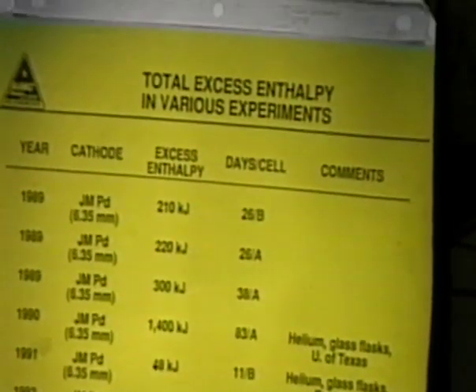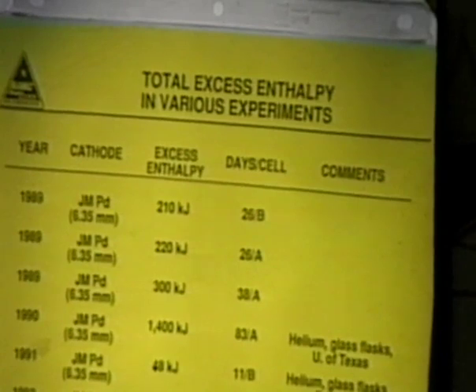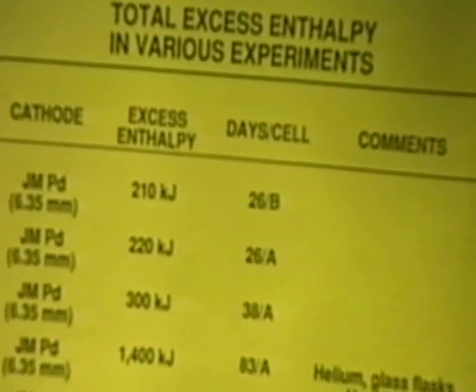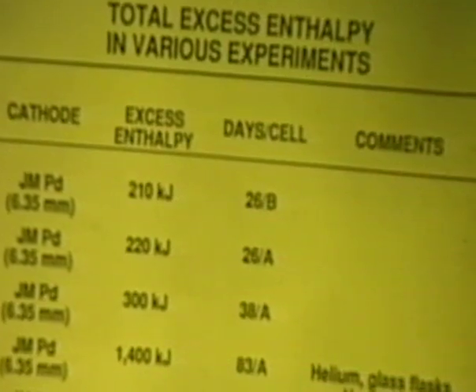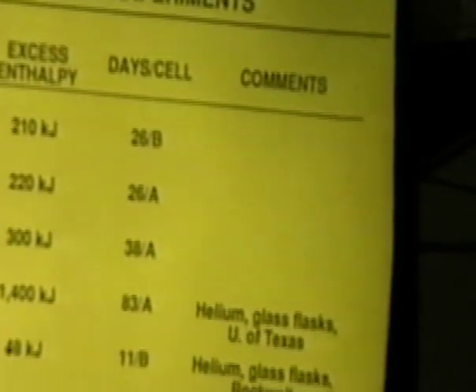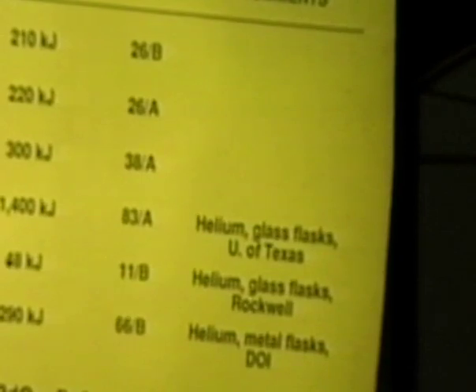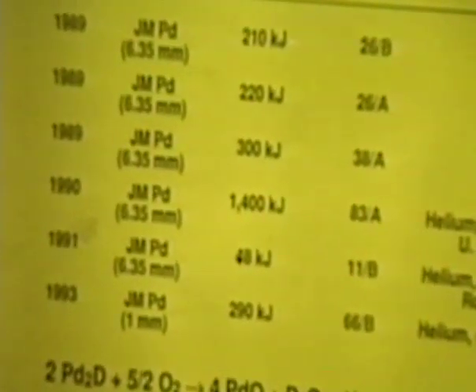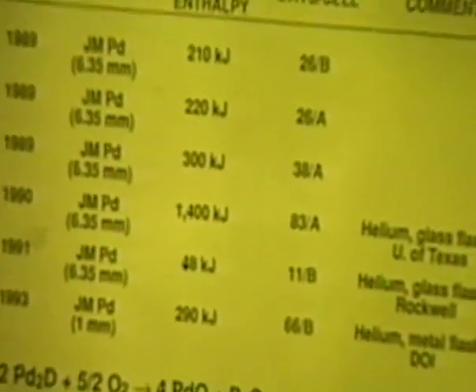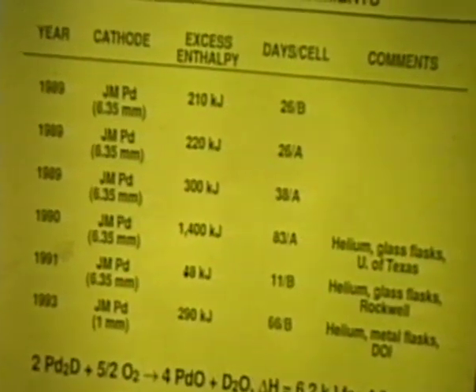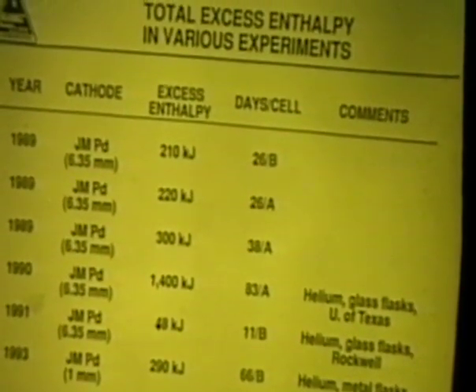And this is our second helium study. This experiment did not show excess heat until after 6 weeks. It took a long time before it showed up. Then it only lasted about 2 weeks before it disappeared. So this gave excess heat, but not for a very long time period. And it took 6 weeks before it even showed up in this experiment right here. And then this is a more recent experiment, and the integrated energy right here.